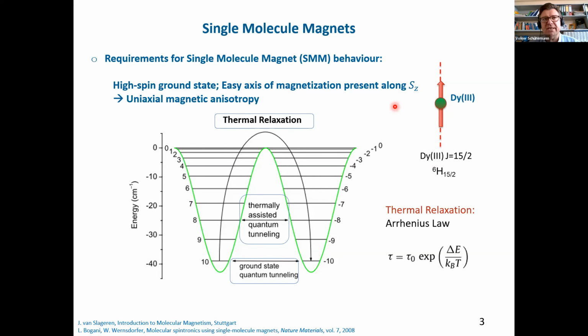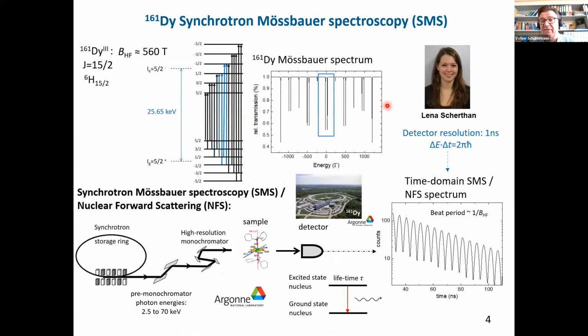However, I should mention there is a Science paper from 2022 from the Berkeley group, Jeff Long. They prepared a dinuclear dysprosium complex, which has hysteresis even at 77 K. So, dysprosium-161 Mössbauer spectroscopy has a complicated hyperfine pattern if you do conventional techniques, but we decided, together with Lena, my PhD student by that time, she's now in industry, to apply the synchrotron nuclear forward scattering technique.